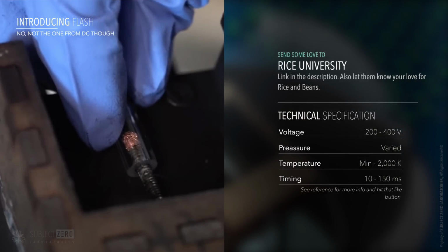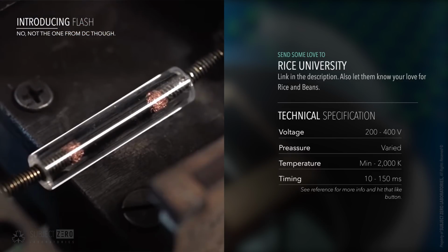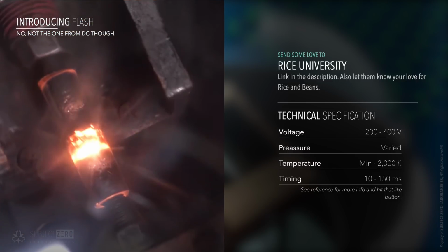Here, they introduce a carbon-rich sample in between two electrodes inside a quartz tube. The sample is then blasted with 200 to 400 volts. This heats the sample up to about 3000 Kelvin, while in other experiments the temperature could even reach 5000 Kelvin. All of this happens in a flash, or 100 milliseconds, hence the name flash graphene.